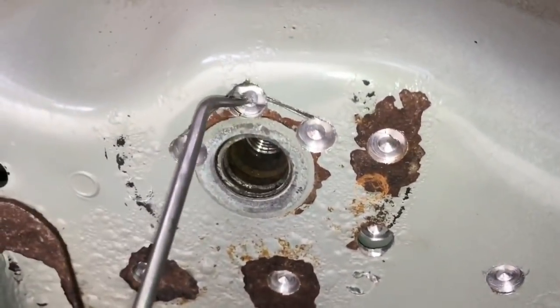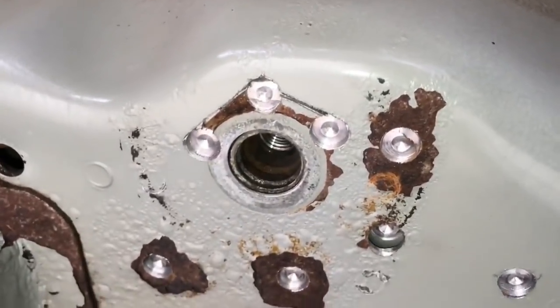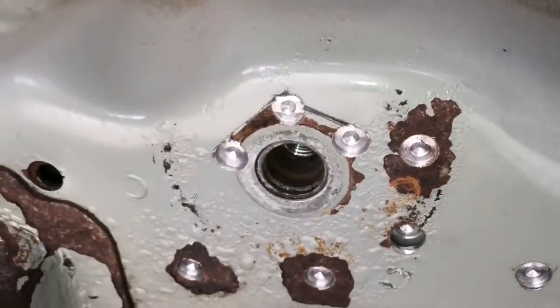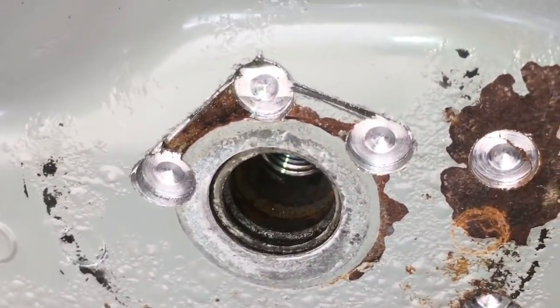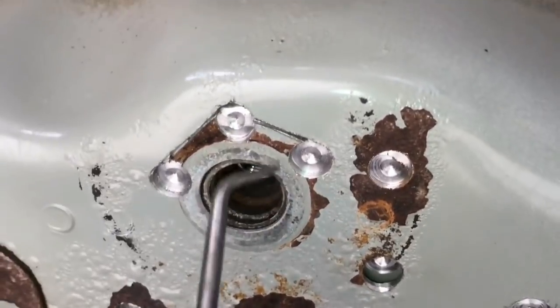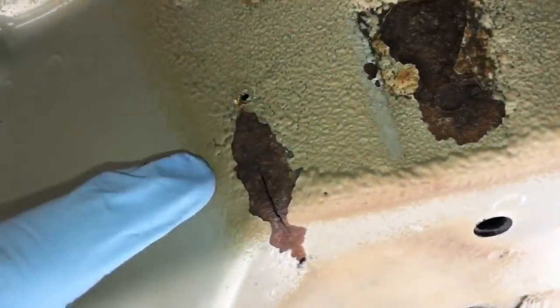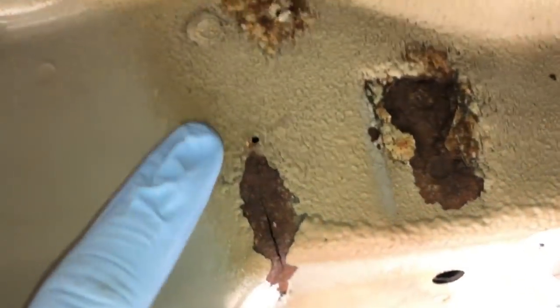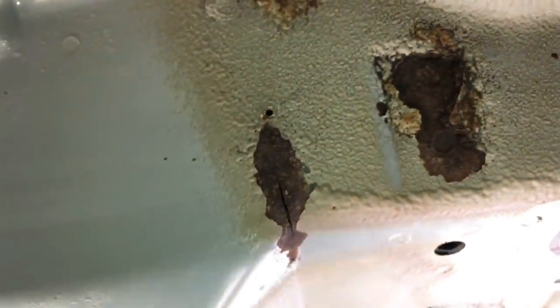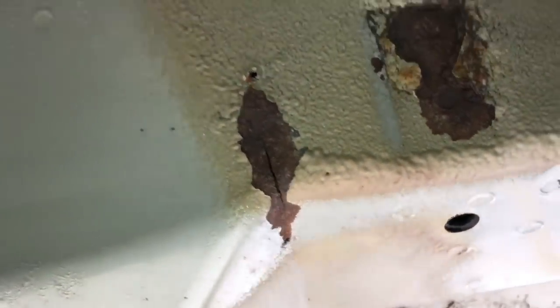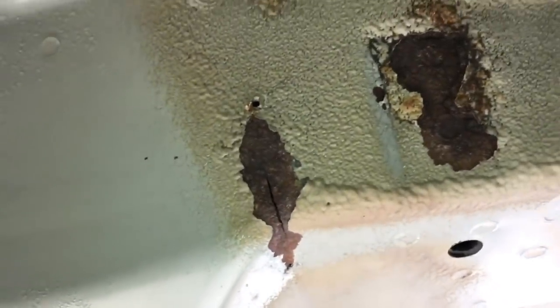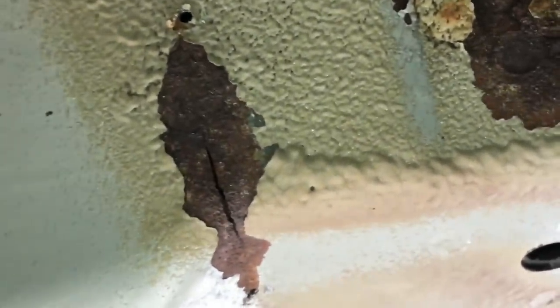Now we're just removing the sections on the front where the crack is around that semicircle mount. There, it just fell out, and the corrosion behind it shows you that it's been cracked for some time. So we just dig that section out now, and also I've stop drilled the crack on the left rear mount down here and down here from what I can see, and that's really important that they're stop drilled, center punched and stop drilled even before you start scratching or removing the seam sealer or the paint, because as soon as you do, you blur the ends of the cracks, and it's really easy to miss the crack or smudge the crack.